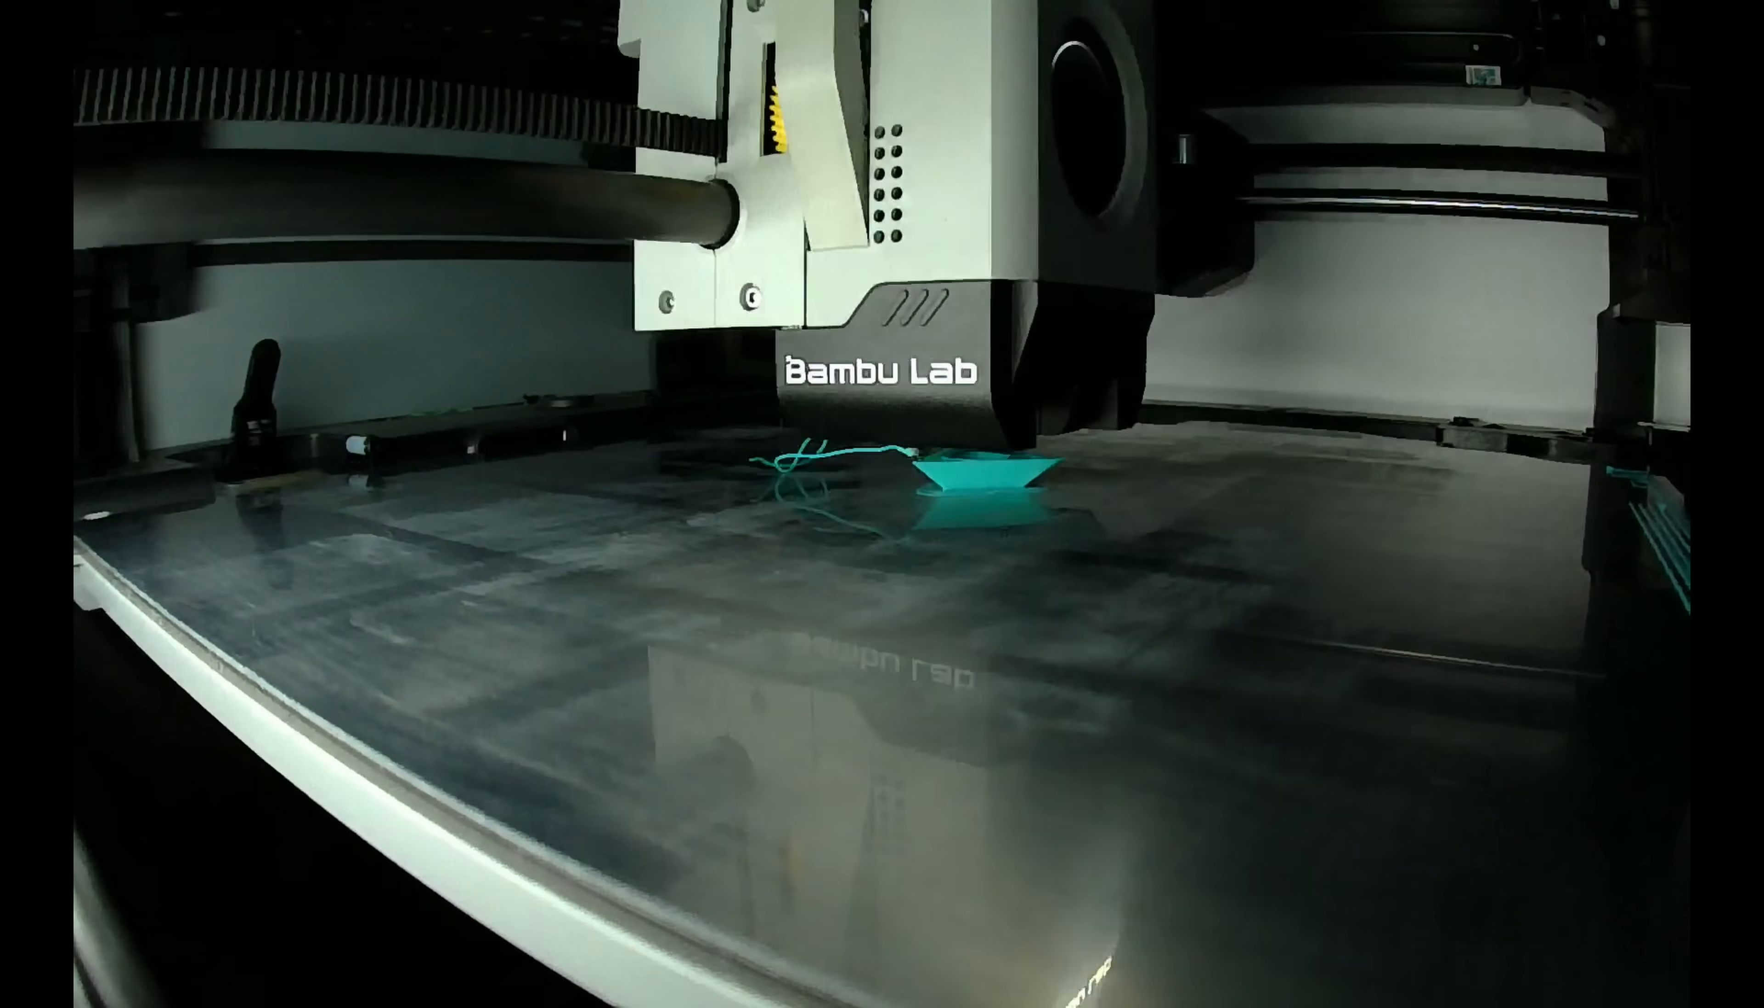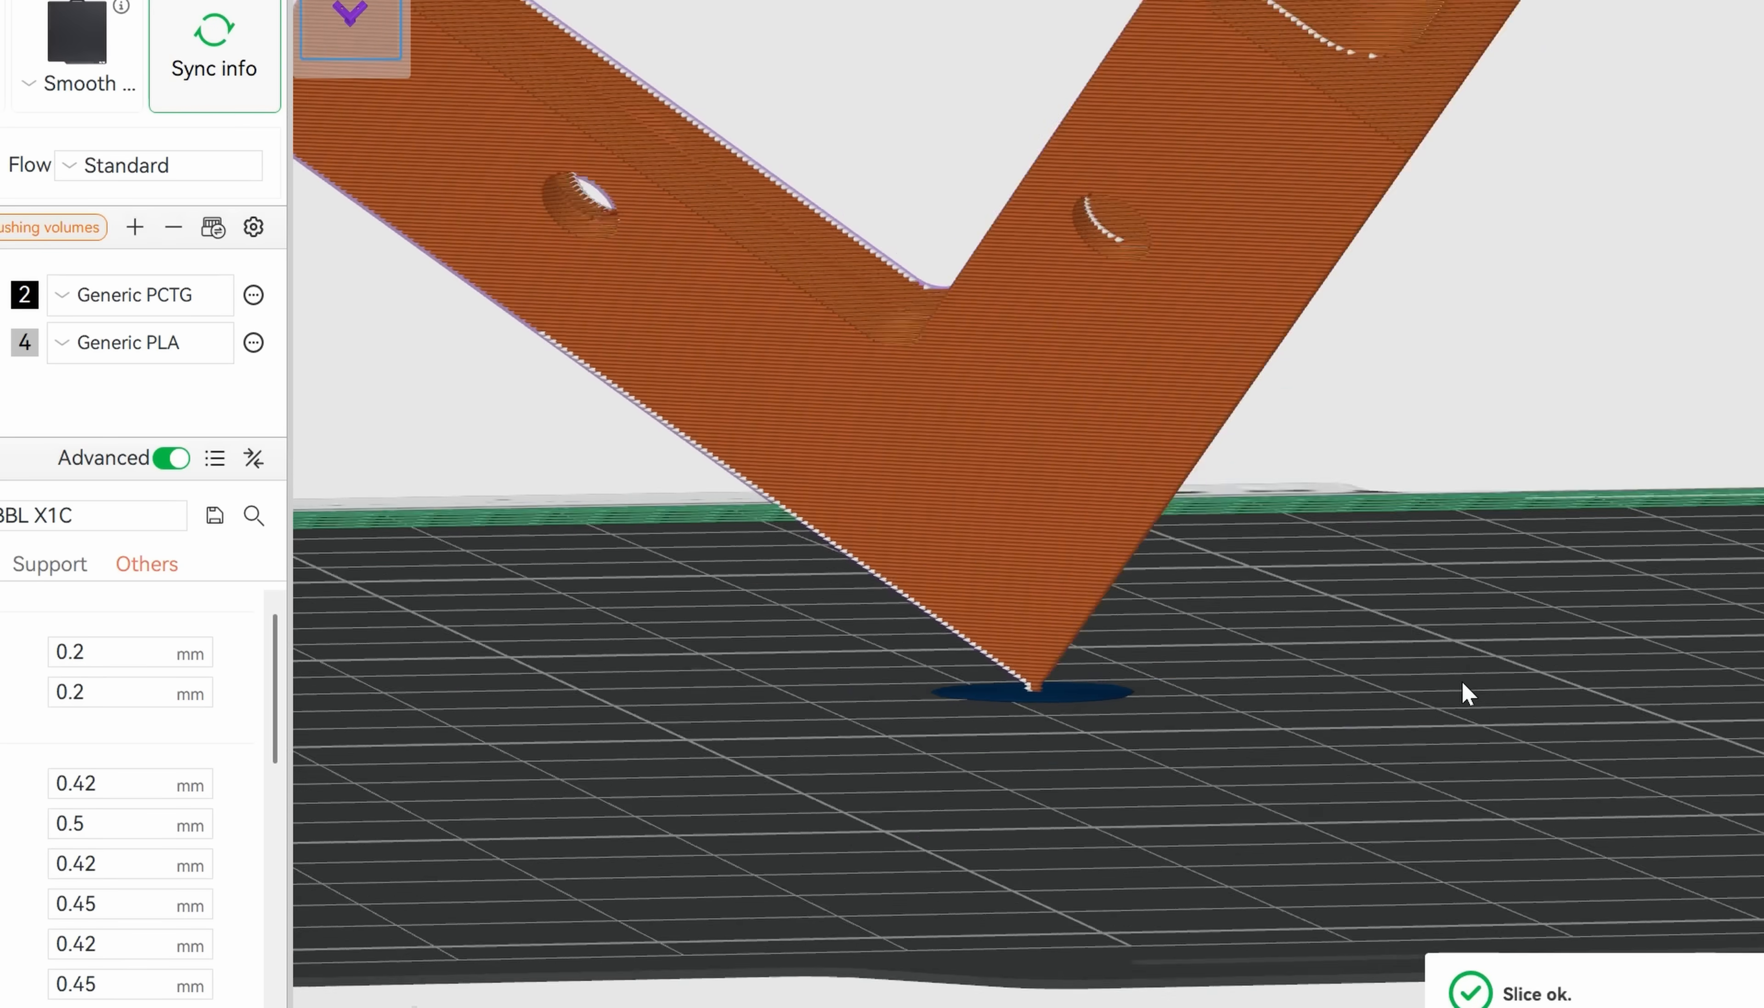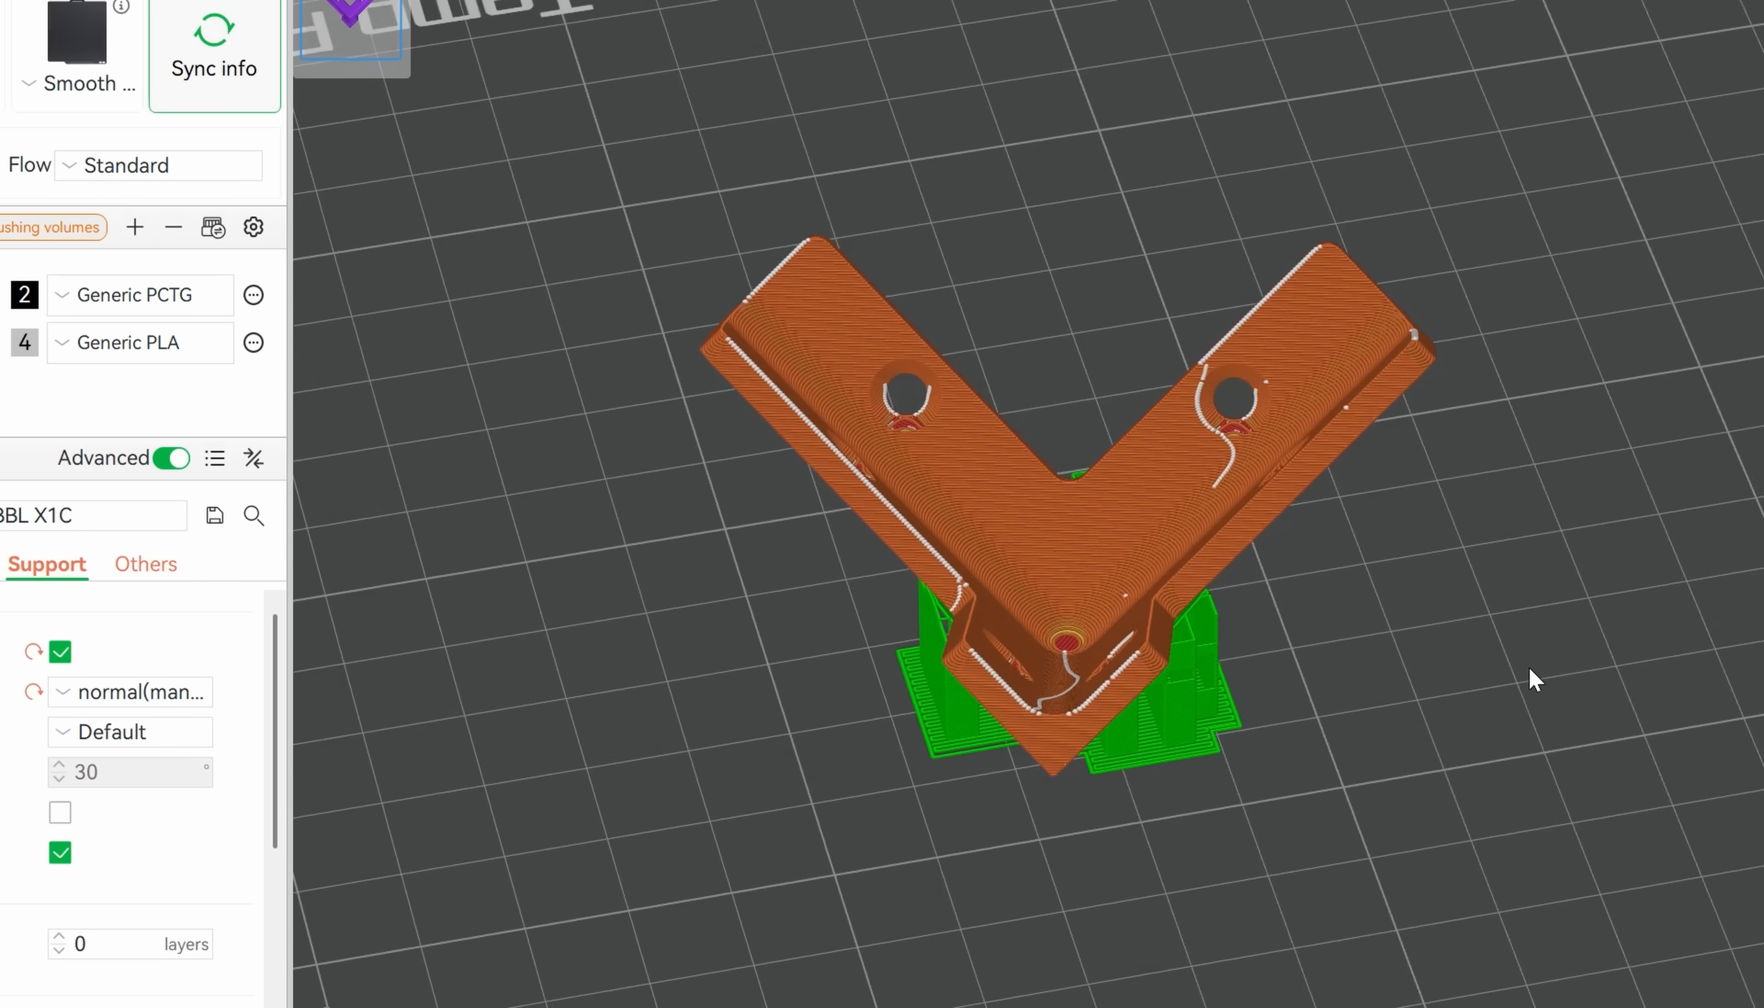So, coming back to our corner bracket. Printing it on its tip will improve the strength of its weakest member while slightly reducing the strength of the others, but that still could be a good compromise. But printing a part at an angle isn't always straightforward though, because it often leads to minimal bed contact. In the case of the corner bracket, just a single point, which obviously won't work. If I didn't design the part myself, I often use a simple slicer trick: rotate the part into the desired orientation and then use the cut tool to remove a small section of a corner or an edge, just enough to create a stable bed contact. Add a brim and with good bed adhesion, that often prints fine, but you can also add some manual support for extra stability.